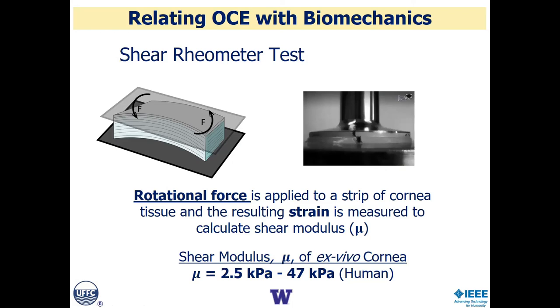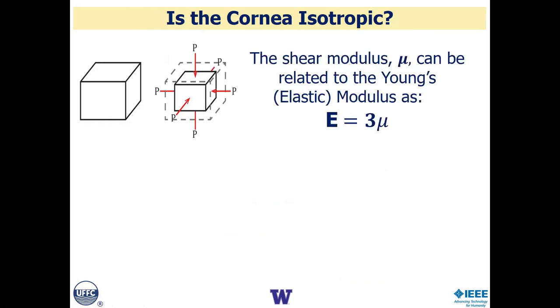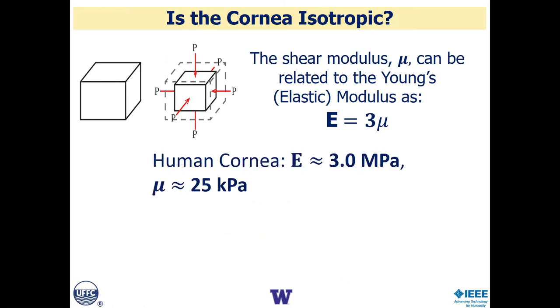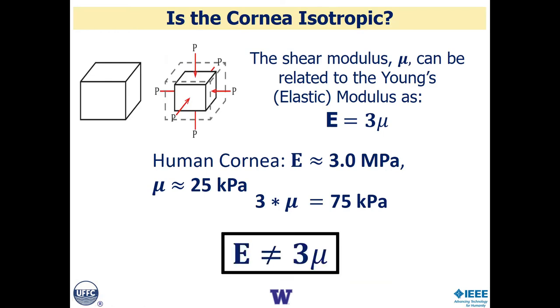So is the cornea isotropic? Well, if it is, then E equals 3 mu in an incompressible or nearly incompressible material. In cornea, E is about 3 megapascals, mu is about 25 kilopascals, 3 times 25 is 75, over an order and a half of magnitude difference. Clearly, the cornea is not isotropic.